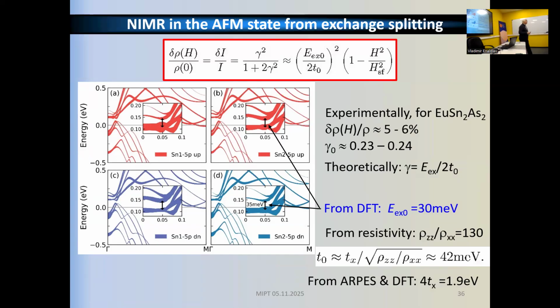Sorry, I missed. So the magnetic moments are parallel to the layers, well, with a certain rotation in between the layers. Yeah, it says antiferromagnet by pi. Yeah, okay. But now you apply magnetic field perpendicular to the layers or parallel. In any direction, you see something like this. Well, the simplest way is to apply it in parallel. But when we apply perpendicular, we also rotate the magnetic moments of europium and then finally tilt toward the field. So you argue, in fact, that applying magnetic field, you have some angle for magnetic moments, and because of that, you feel the exchange energy. Yeah, that's it. Yeah, okay.